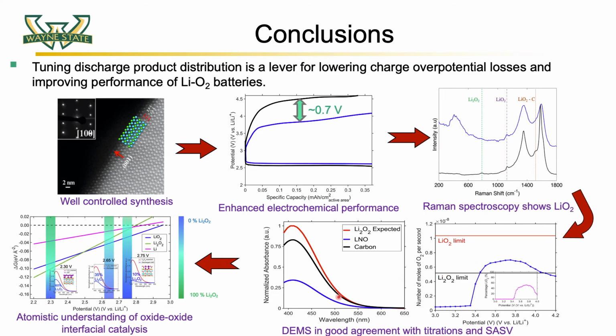Quantification techniques like titration and electrochemical mass spectrometry indicate that more than 60% of the discharge species is due to the selective formation of LiO2 during discharge. These experimental insights are then benchmarked using theoretical calculations, which suggest a stable and favorable formation of LiO2 till a discharge potential of 2.5 volts.